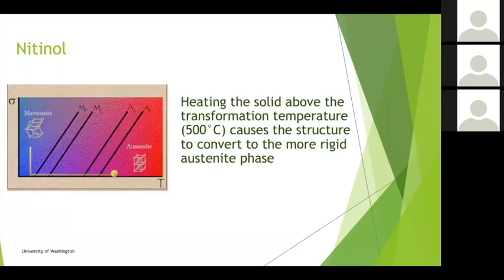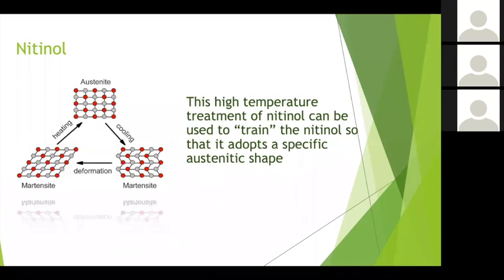So I have to take this martensite phase and heat it. This high temperature, generally above 500 degrees Celsius, will cause nitinol to convert from a pure martensite phase into this austenite phase. And this is where the metal becomes more rigid. It's through the heating of the metal that it changes the molecular structure, and now we have this more rigid metal. At this high temperature, we train nitinol to remember its specific austenite phase or shape.